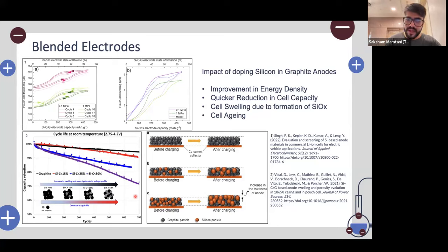The other drawback, apart from the capacity retention, is the swelling of the cell. If you look at this particular figure, it gives a very good imagination of what happens inside the cell if you're doping silicon. After you charge the silicon, silicon oxide has a tendency to expand. And that's why the electrode material ends up swelling a little bit. This swelling is of two types. It can either be reversible or irreversible based on the type of losses that the electrode encounters. That depth is not what we are going to go towards in this particular talk. However, this is definitely a huge drawback. And if this is an irreversible swelling, then the cell is going to swell up very quickly.